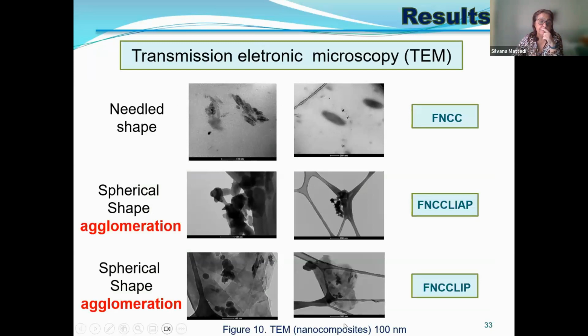And here is the transmission electron microscopy of the material. The first part was only using the fibers, and here are the nanocomposites, so here we also have the polymers. For the protic ionic liquids and for the aprotic ionic liquids, although here the fibers were cylinders, when it goes in the material, it has a spherical shape, and you can see some agglomerations forming in the material. The same thing we can see for both ionic liquids, but it does not occur when you use the sulfuric acid.